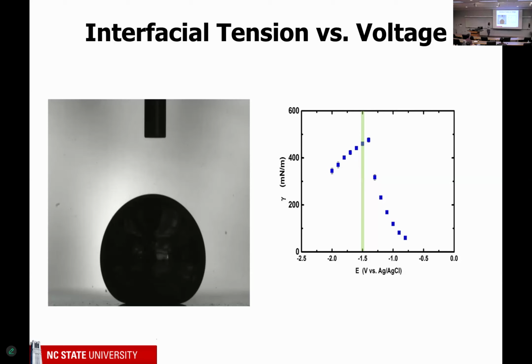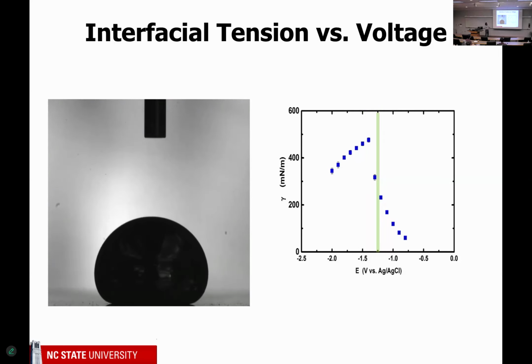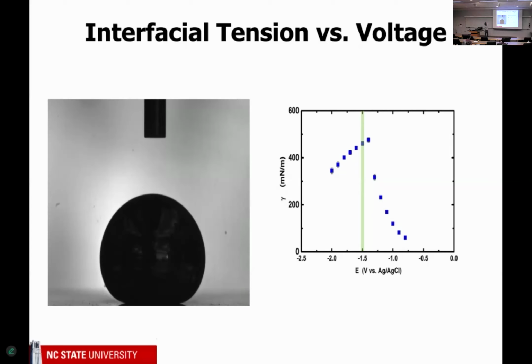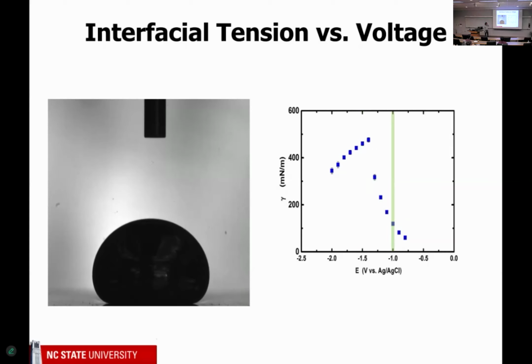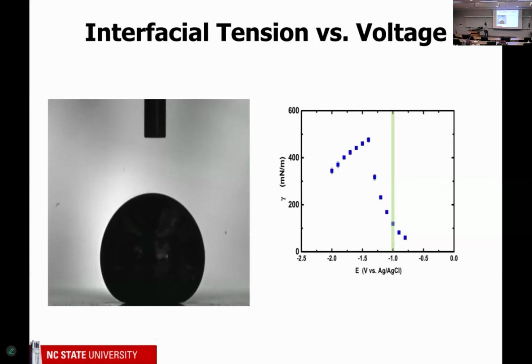And so when we apply voltage, you'll start to see that the tension lowers, the droplet squishes, and then it goes even lower. So we apply more voltage, but it's completely reversible. And we can go back and forth. This is real time. It's very fast. And so we're getting absolutely enormous changes in surface tension by just applying a fraction of a volt. So, okay, so what's happening?